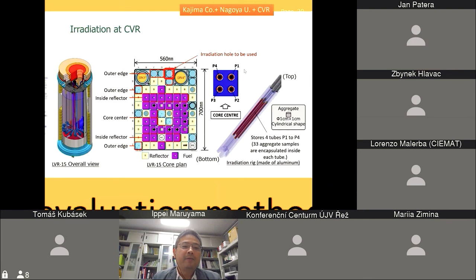We are using the LVR-15 reactor, and as it is recommended, we put the samples in this hole. This is the irradiation rig, and we put 33 aggregate samples encapsulated inside each tube, and we put 4 tubes in one rig. So this is a very smart way of irradiation. After getting the data, we will try to analyze which kind of rock formation is very tolerant to the neutron irradiation, and what contributes to the expansion of aggregate.